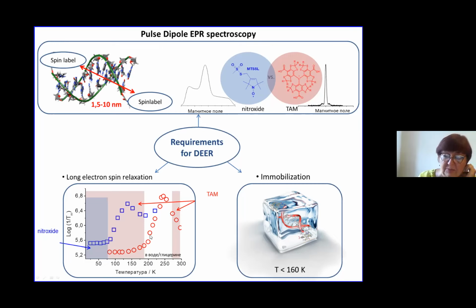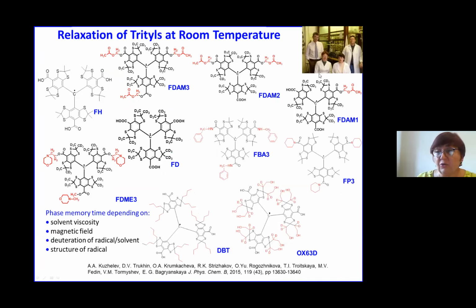And why is that interesting? Because of electron spin relaxation; here you see the dependence of electron spin relaxation on temperature. You see that for trityl radicals, it is much longer. And that was the idea. And another idea was, as I said before, Viktor Tormyshev is very, very skilled in the synthesis of a great variety of trityl radicals. He can substitute in different positions, different compounds, deuterium or other, and by this substitution, one can make radicals either water soluble or hydrophobic or hydrophilic, and also change, for example, if we need some constant here for some project,